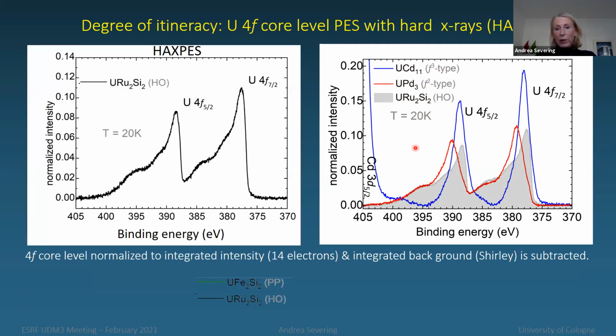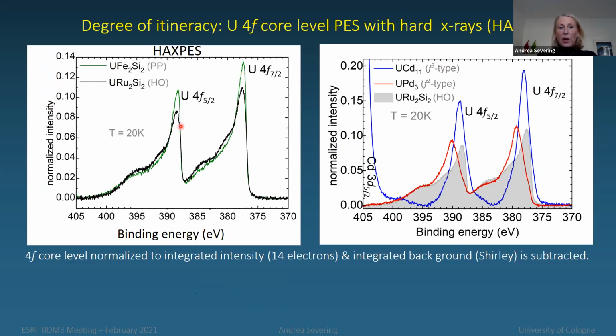And now let me come to the comparison with the other materials. Again, I'm showing the uranium ruthenium two silicon two. These are the same data as I'm showing here. It's only a sort of spread Y scale. And now I'm showing you the uranium iron two silicon two, the Pauli paramagnet. And what we see is we see more intensity here. And this is where the cadmium 11, where the F3 is more pronounced. So we have a shift from F2 to F3. We have less intensity here and we have more there.